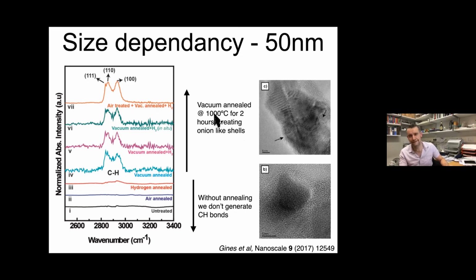It's high, right? It's 1000, maybe a bit more. What you see in the TEM is you start to see, of course, all this graphitic stuff start to appear, these sort of graphene-like shells or whatever you want to call them. And then if you try and heat them in hydrogen, you start to see the CH stretch. So it starts to react, right? So that's a red flag to me. Basically, you need the sp2 to drive this reaction on the surface, okay?